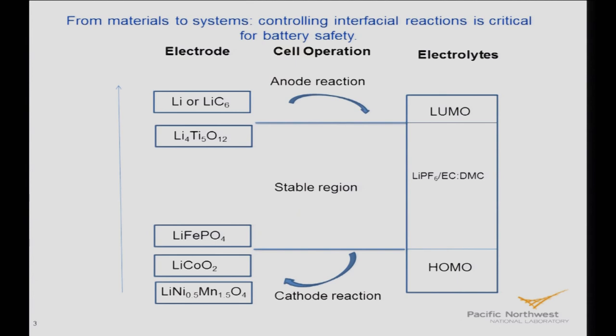I don't know how to make this work, but on the left-hand side, we show the chemical potential of the electrolyte, and the other side shows the chemical potential of the electrode material. Top is the anode and bottom is the cathode. As you can see, if you look at the so-called LUMO and HOMO energy levels of the typical electrolyte and compare that with the energy level of the electrode material, ideally you want to be working within this stability window. Otherwise, you get into trouble.